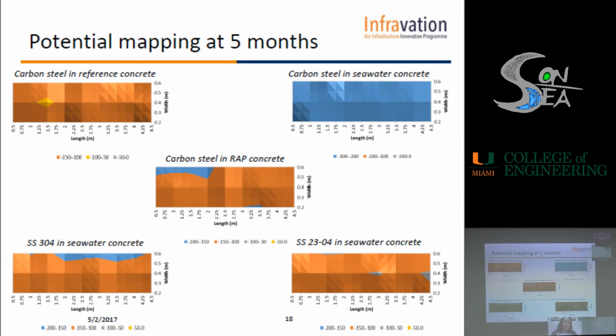So with the potential mapping, we can see whether the condition is the same also in the areas that are farther from the probe. Actually, we can see that the variation in the potential gradient inside each segment was only of a few tens of millivolts. So the potential was quite uniform in all the segments. And so we can consider that the results that we obtain from the probes, at least so far, can be considered representative of the conditions in all the segments.